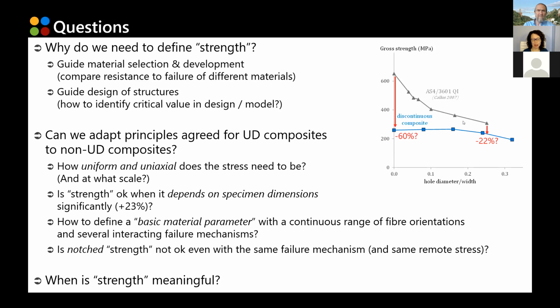So in my opinion, it needs to be unambiguous. And this is when having standards and defining exactly the conditions in which we measured that strength is important. And in my opinion, as long as we define a strength unambiguously, and for each material we can have many definitions of strengths, and for each structure we can have many definitions of strengths, as long as those definitions are useful, and I say useful either to compare different materials or to help us designing structures, I would say that any definition of strength that fits those two criteria, so unambiguous and useful, is a measure that we should probably use.